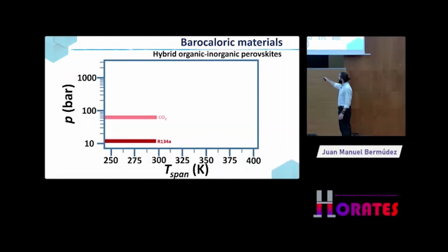These two are refrigerant gases. As you can see, they work near room temperature in a wide range. Okay, this is CO2. For CO2 you need more pressure to operate. And if you compare this temperature span with that of the metallic alloys, even though they work at room temperature, the span largely decreases for the metallic alloys. That's obvious because you need more pressure to induce the phase transition. So the phase transition is not going to shift that much for metallic alloys.